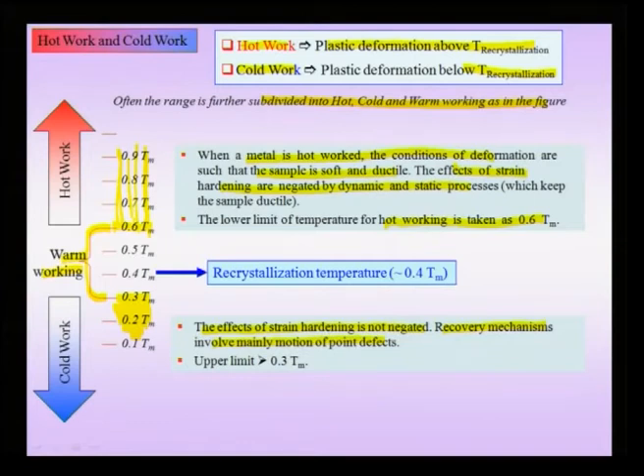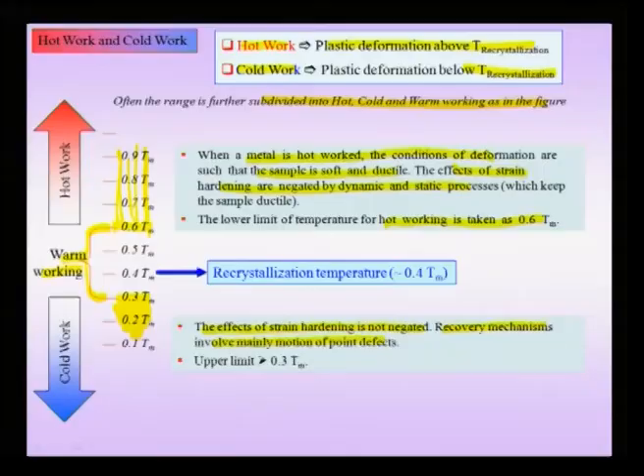So, if a person wants to increase the strength of the material, he would do cold working. On the other hand, if he wants extended deformation of the material without any intermediate processing steps like recrystallization, he would actually do hot working of the material. Somewhere between the two is typically quoted as the recrystallization temperature, which is about 0.4 Tm.